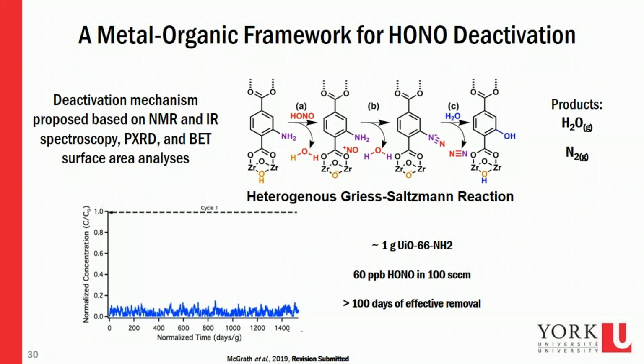We're pretty confident that this is what's going on. We can see a lot of these intermediates by different spectroscopic methods, powder X-ray diffraction, and looking at the changes in surface area over time. So it seems pretty effective at essentially denoxifying, not really dehonoifying, an exposure stream of gas. Just to give you an idea of what that is from this particular plot again, we loaded about 1 gram of UiO-66 that's amine functionalized, exposed it to 60 ppb of HONO and 100 cc's of gas flow, and we had over 100 days of effective removal and saw no signs of breakthrough.